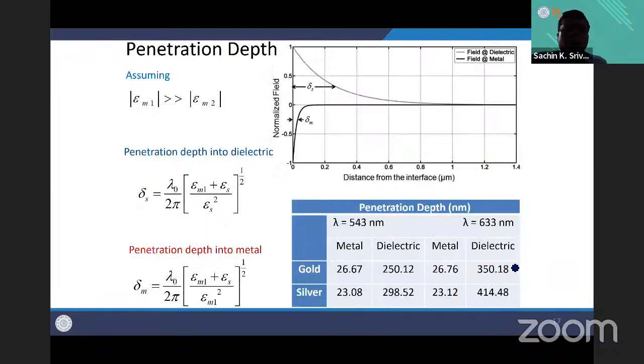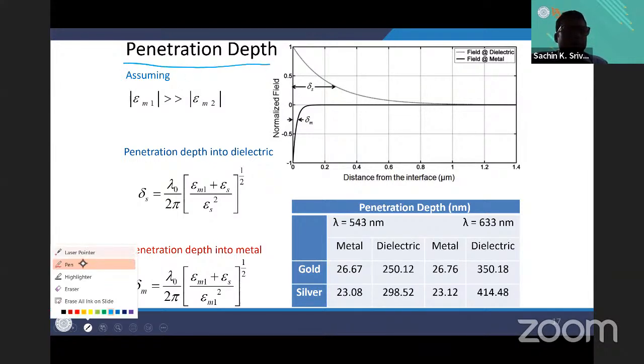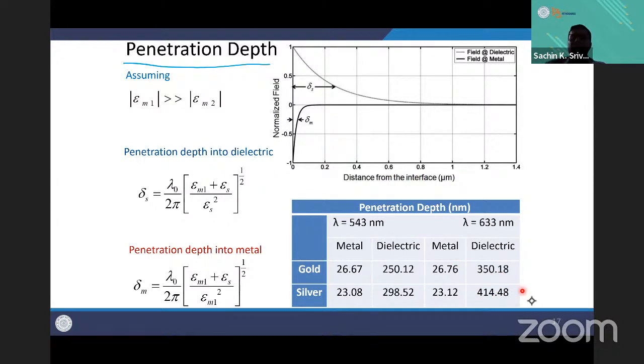Now the field also, I told you, decays rapidly if you go away. So that is called penetration depth. You can see that when you have, for example, gold and water, for the metal it decays very rapidly, from here to here. It's called penetration depth. And it goes up to, let us say, 250 nanometers or 300 nanometers for silver. If you increase the wavelength from 540 to 633, you can see that this is hardly changing. It is like 26 again here, almost the same, but here it changes. So you can control the penetration depth by controlling the wavelength of the incident light.